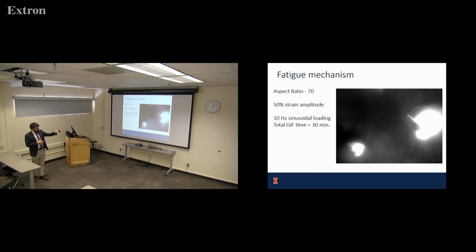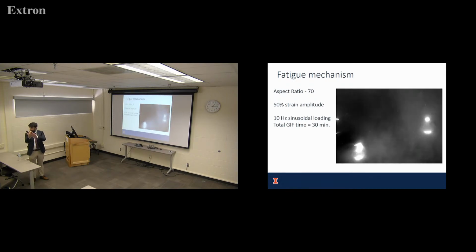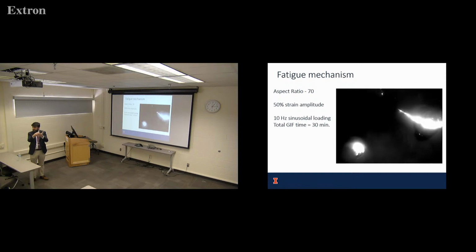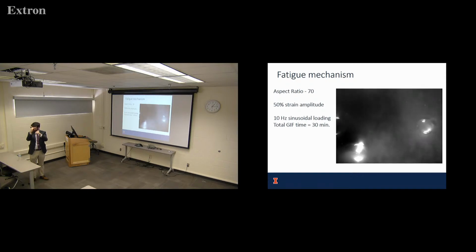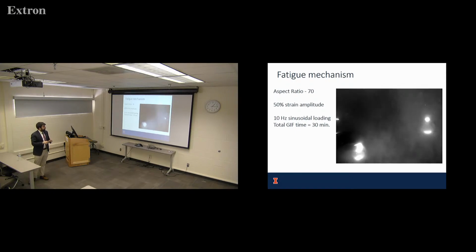I think when it's very bright like that, that's actually the back plate scattering, the top plate. You're seeing the bottom because now there's a cavity there, so there's just such a thin film of binder that you're starting to see the bottom of the top plate through it, because the camera is coming from below, and on top you've got the binder sandwiched between the cylinder and the slide. So you're seeing the bottom of the cylinder, which is scattering a lot. I think that's what's causing that bright scattering in the beginning.